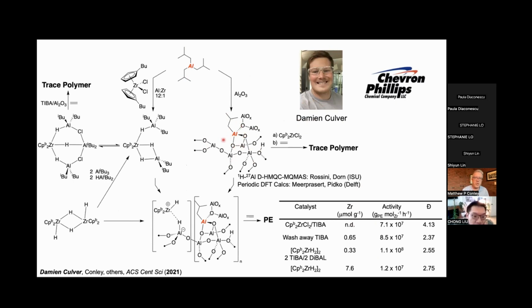These look like partially hydrolyzed aluminum alkyls because that's what they are. So we were nervous that these were actually the activators responsible for the olefin polymerization chemistry. We contact with the metallocene dichloride, then ethylene, and nothing happens. So that we can rule that out pretty quickly.